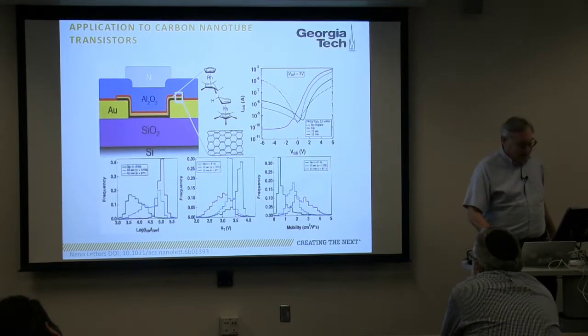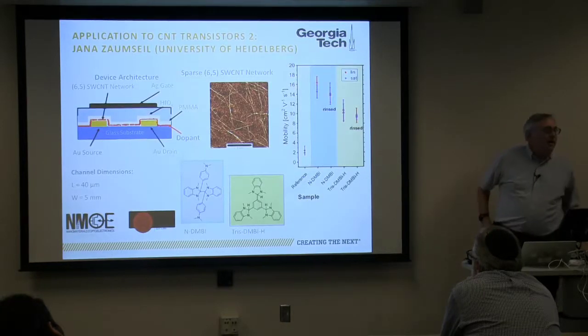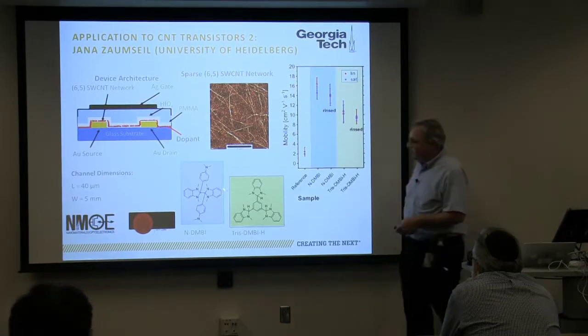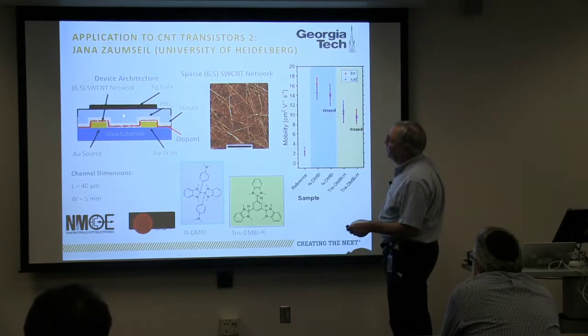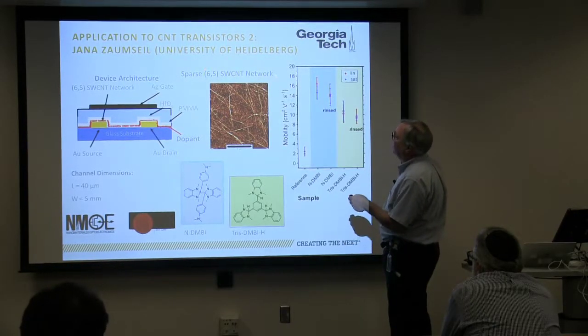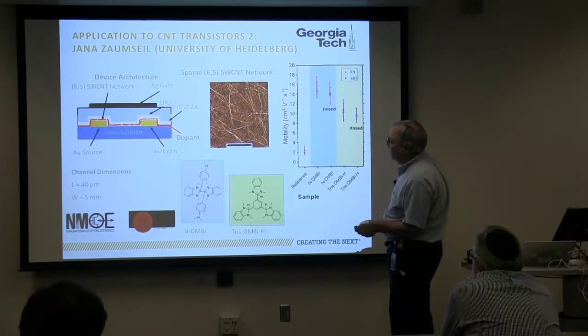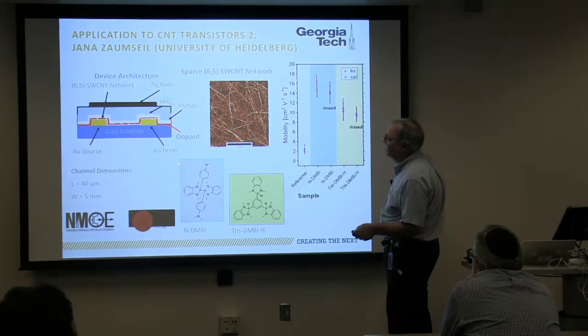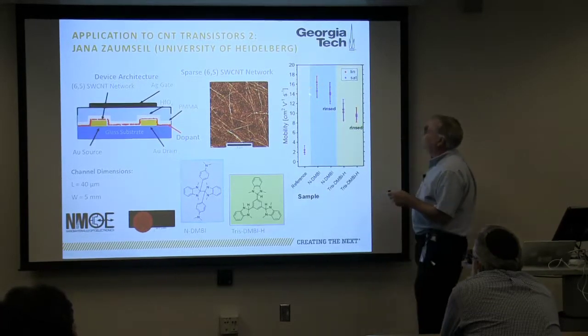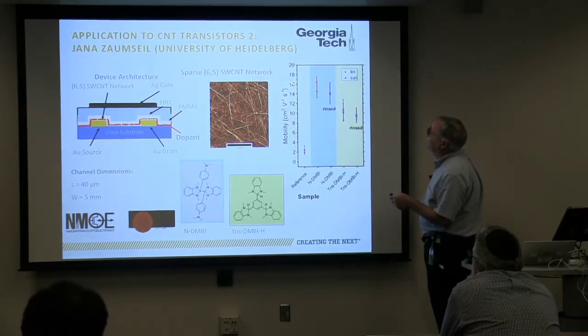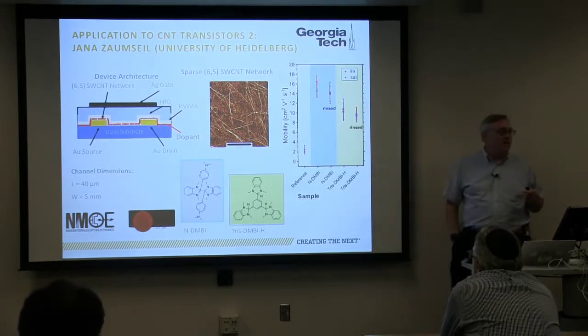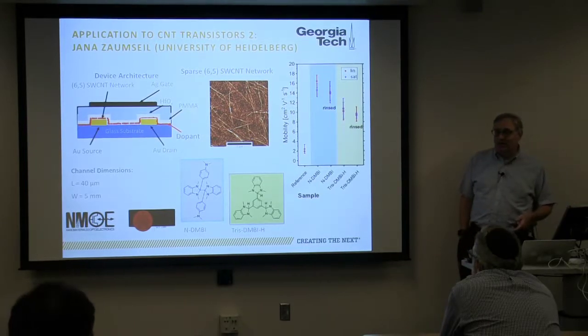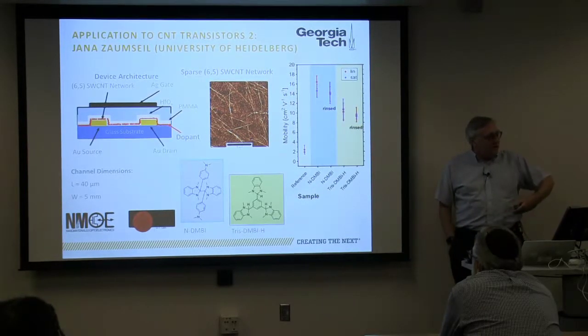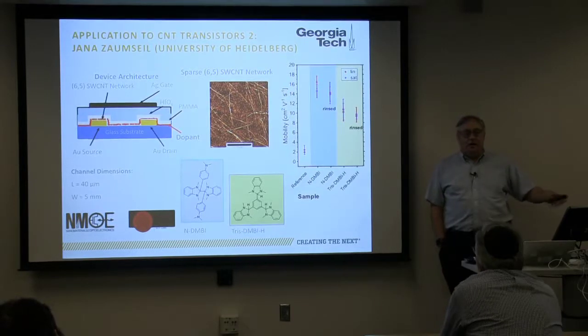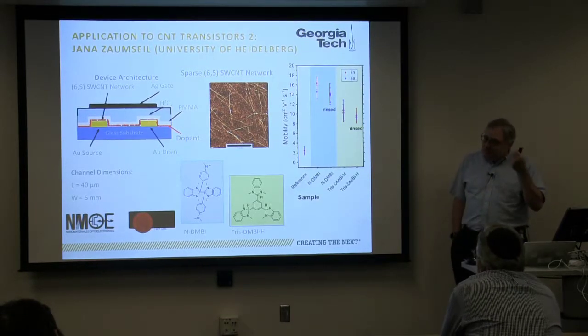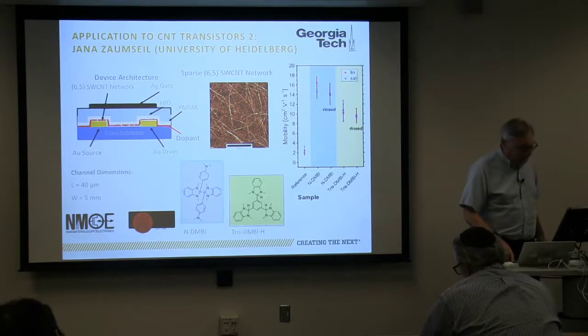Then a colleague, Jana Zaumseil, has looked at another one of our dimeric dopants, in this case based on an organic material, with somewhat different architecture and slightly different nanotubes. And what she's been able to do is, again, take p-channel transistors and dope them. And now what they're seeing are mobilities on the order of 10 to 15 centimeters squared per volt second. So what we've done is we've taken a perfectly good p-channel material, and we've used just a trace of dopant to change its characteristics.